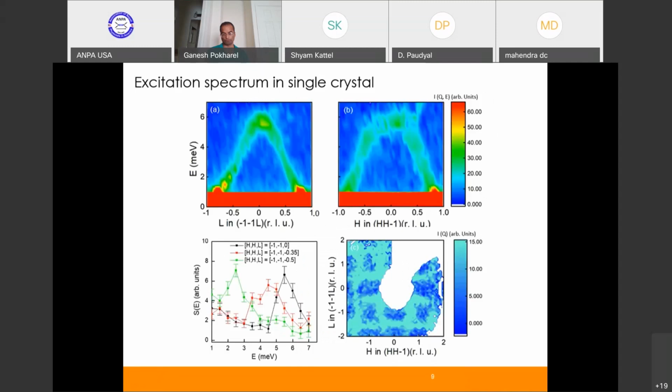These are the spin waves which I measured from the co-aligned single crystals. The first two figures represent the spin wave along the high symmetry directions 001 and 110. The spin wave along the 110 direction shows some sloping feature or asymmetry around the zone boundary.